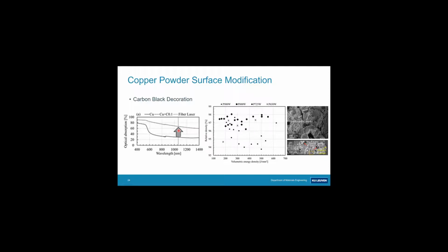Besides that, since there was still carbon present, liquid copper and carbon do not wet each other, we could find back carbon at the borders of every melt pool. So it basically means from the moment your laser beam irradiates your carbon-coated copper powder beds, you create liquid copper at a certain point. No wetting occurs between the solid carbon and the liquid copper. The carbon segregates to the melt pool boundaries, and your laser effectively shines on a very pure copper melt with all its consequences, meaning a lot of back reflection and the requirement for very high laser powers.